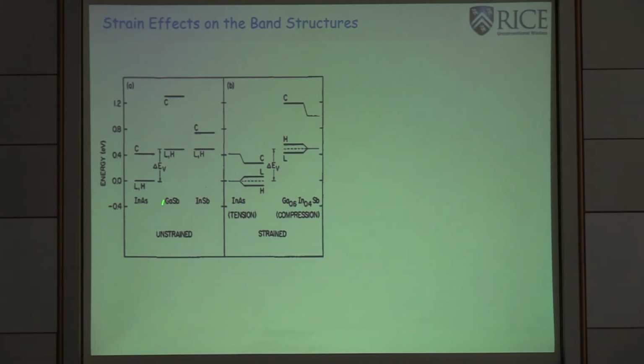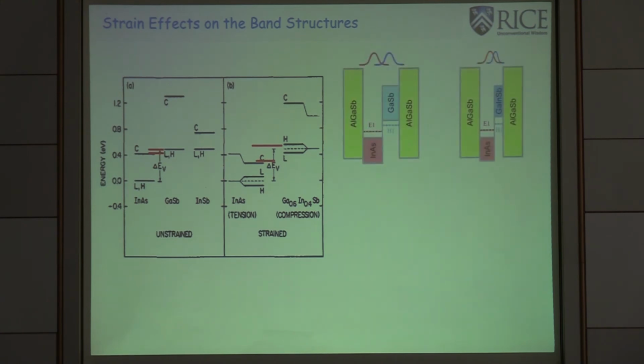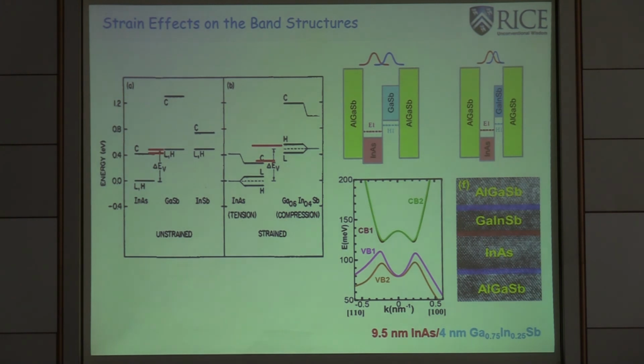Here is a specific diagram showing how much change in terms of the energy. From this, we can simply say that under the compression strain, because of the mismatch between these two quantum wells, the inversion of the band is going to dramatically enhance. So it became more inverted. Once more inverted, in order to bring it back to the same alignment, the way is to reduce the thickness of those quantum wells. So initially, a wider thickness allows you to make thinner quantum wells to bring it back to the same alignment. And in this case, because this is thinner, the wave function is much more strongly overlapped. Therefore, this helps to enhance the energy gap due to the hybridization.